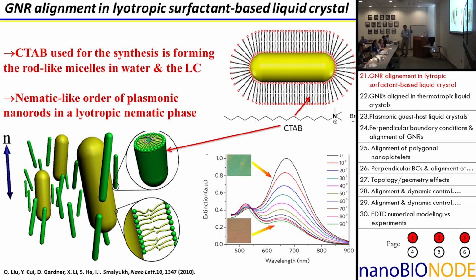And now, if you would observe such a dispersion through a polarizing film, you would see the color change, right? Because not only individual nanoparticles now have those polarization-dependent properties, the rod-like nanoparticles we discussed before, but the entire medium is inheriting those properties of individual nanoparticles. And so you can see the spectra with transverse and longitudinal surface plasmon resonance peak that change as you are changing the polarization of light that you use.